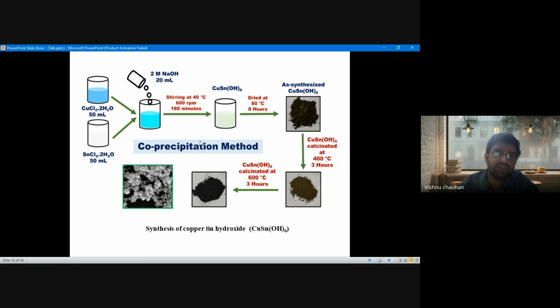Initially, we take the two precursors, copper chloride and tin chloride, and mix them together. Then we take 2 mole of sodium hydroxide, add it to 20 ml water, and stir together at some optimized temperature for a few minutes. Here we have taken 180 minutes. Further, we got the solution. The solution is dried at 80 degrees Celsius for 8 hours. Then we got the synthesized powder.